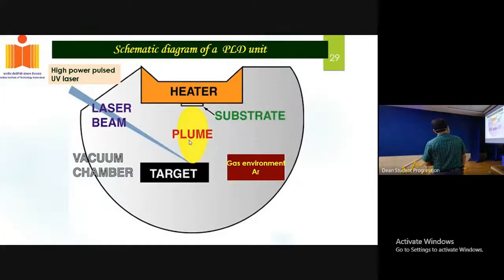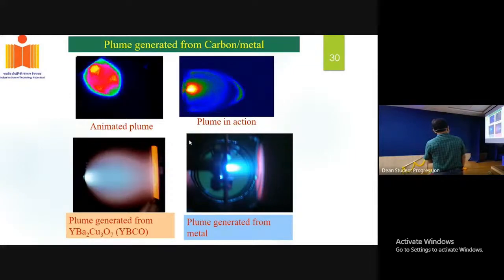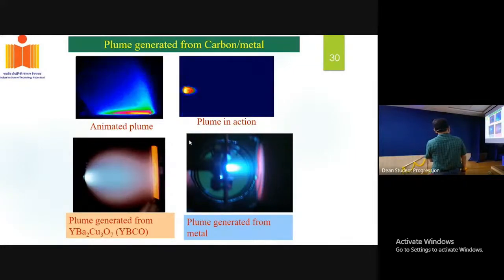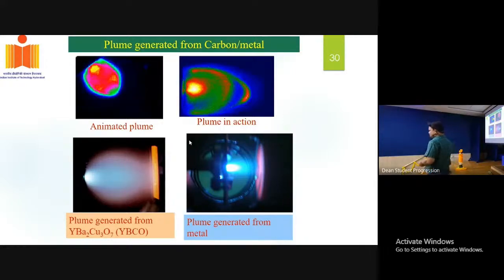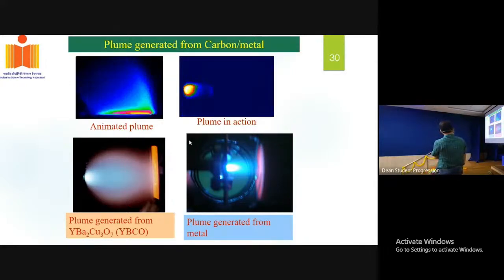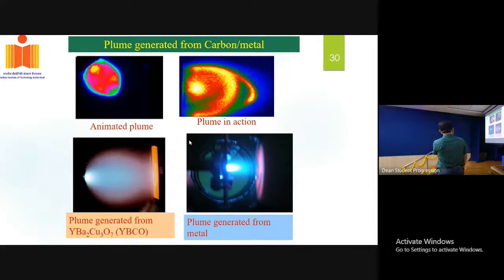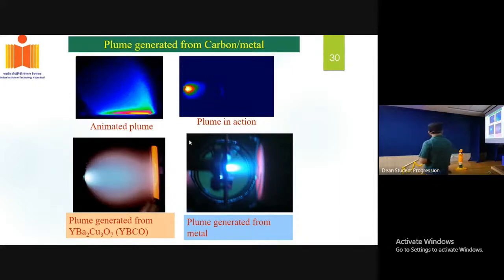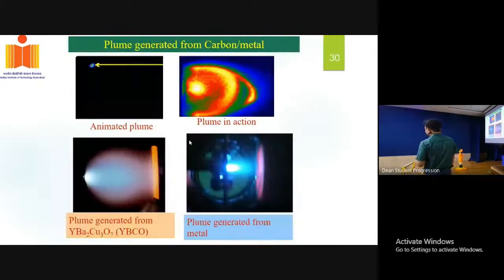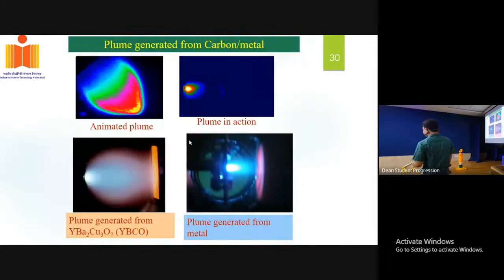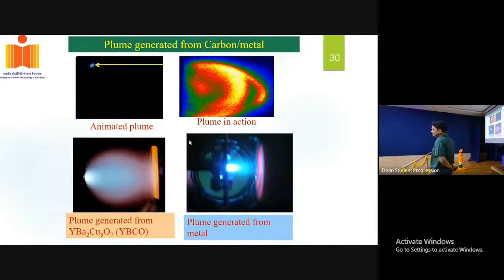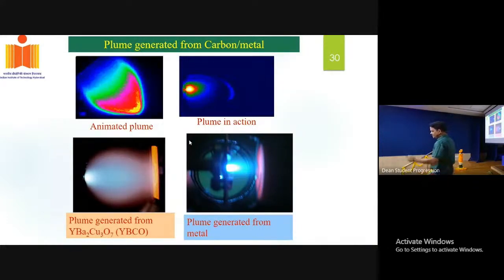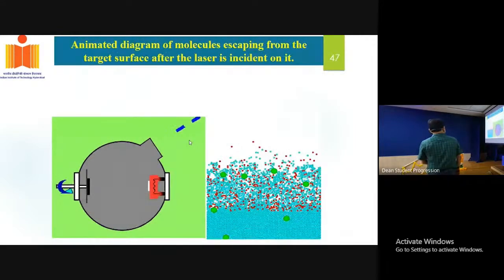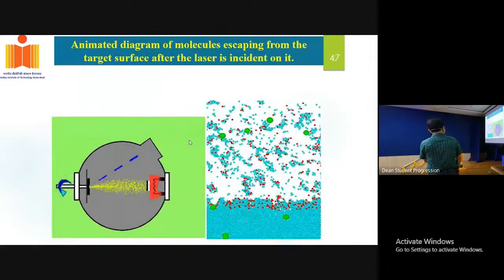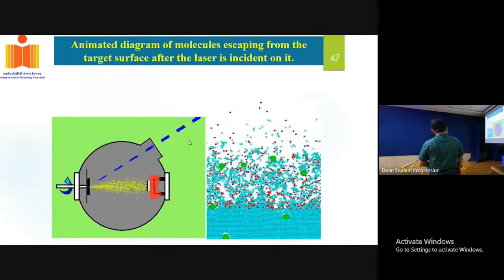The laser will fall on the target material, and then the plume will be developed, and this plume will go and deposit on top of the substrate. Again, this is a plasma. This plasma will go and deposit. This is the kind of plasma you can imagine. It will go and deposit on top of the substrate material. Particularly, PLD is famous for depositing oxide material, whereas sputtering is very good for depositing the metallic thin film. The moment you impinge laser on top of the target material, there will be breaking of the bonds from the surface. This material will go and deposit on top of the substrate surface.